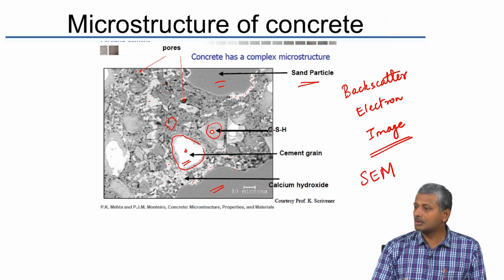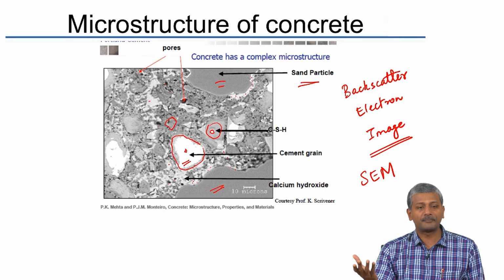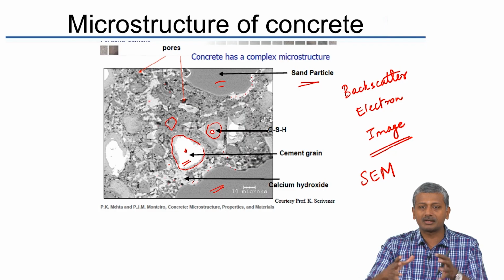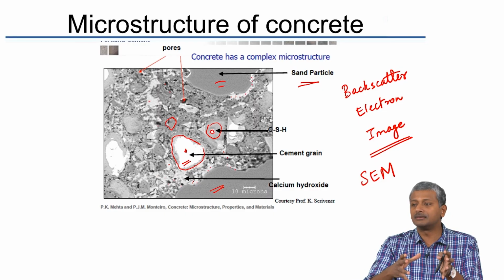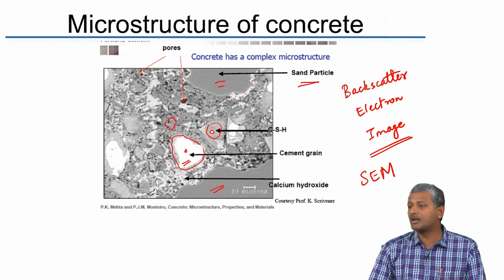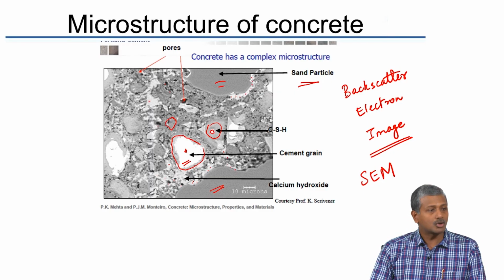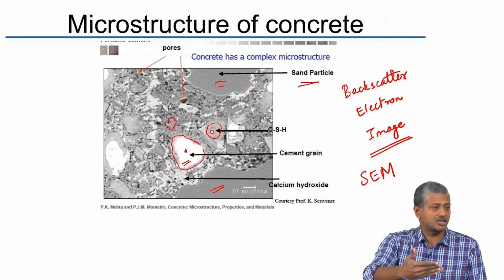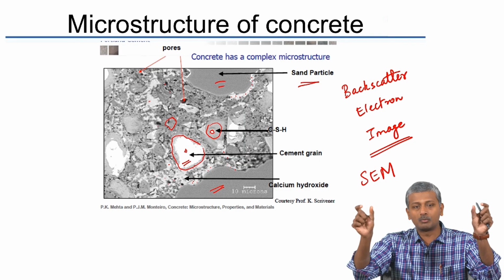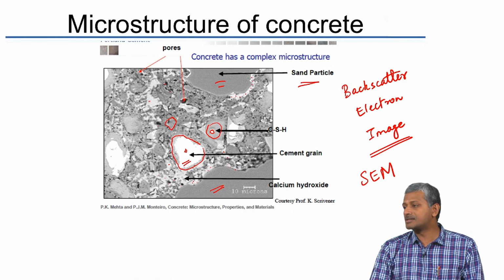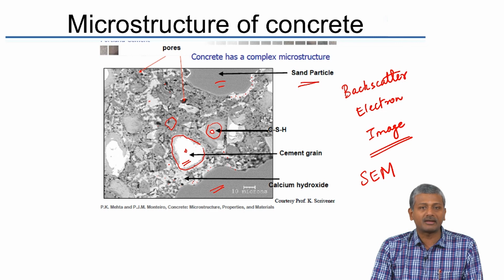So, again, when you are, for example, conducting your experiment with aggregates in the lab, you pack your aggregates in this cylindrical container, you pack it in layers, you compact the layers and so on to determine the unit weight or bulk density of the aggregate. Now, what you will see, if you have a way of taking a snapshot of the cross section, is that the voids and pores left behind on the edges are much more than what is towards the inside, and that is generally a tendency for packing to happen like that.